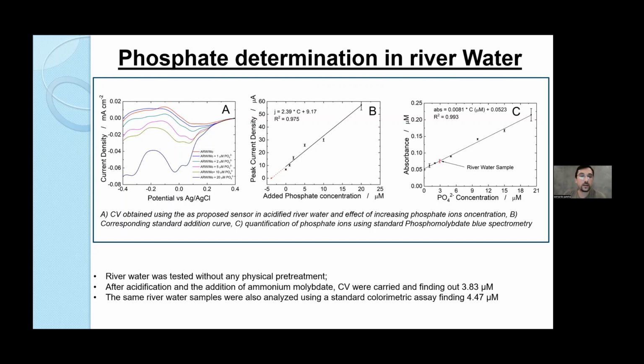But in order to compare our result with a standard technique, we have carried out the standard colorimetric assay with the phosphomolybdenum blue reaction, and we found a concentration of 4.4 micromolar. So the two methods gave the same result, 3.8 and 4.4 micromolar, suggesting that our sensor gave results very, very close to the standard technique. So it can be used as a real alternative to this analysis.